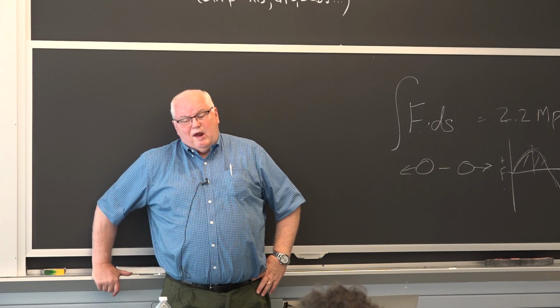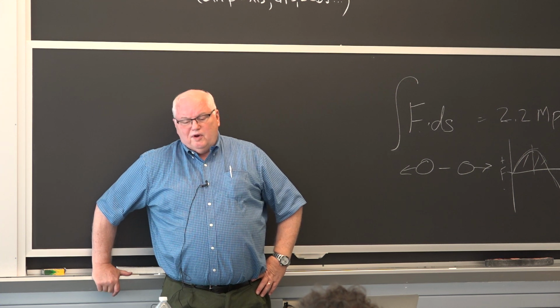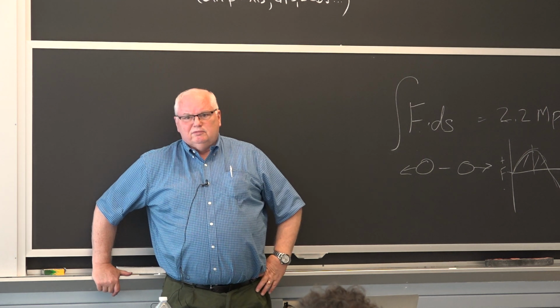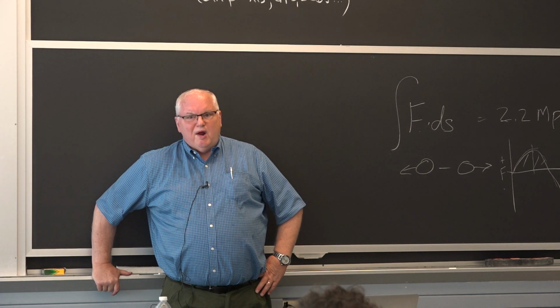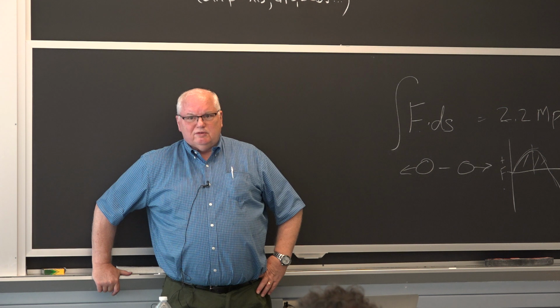If you're talking about a ceramic, I had some guys in the office from a company last week, and they're trying to make better ball bearings for jet engines. They want to make them out of silicon nitride because it's one of the toughest ceramics. But the size flaws they've got to be looking for, 5 microns in size, because 5 microns will be a critical flaw size in fracture mechanics for a ceramic. For a metal, maybe half an inch, 2 inches is a critical flaw size.